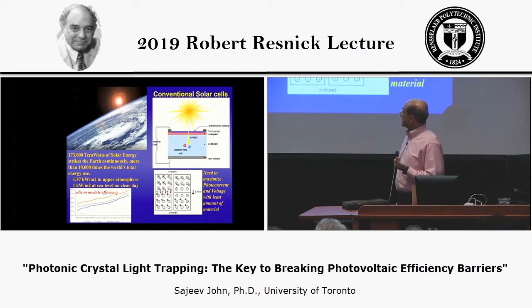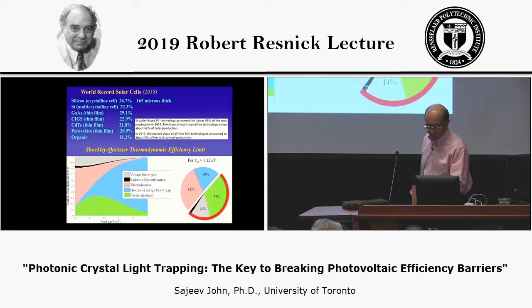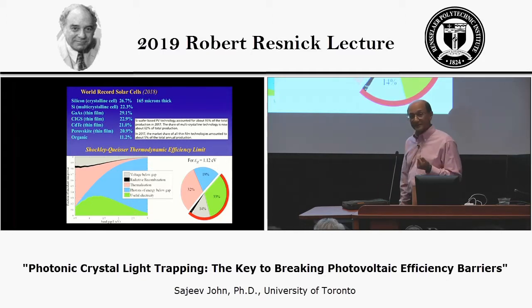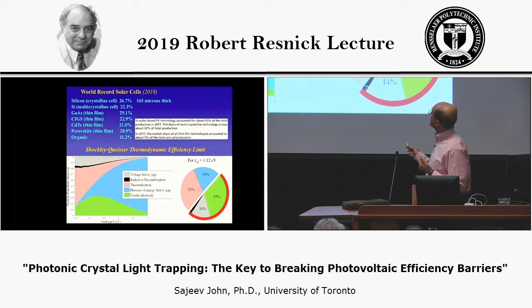And typical silicon materials that we have right now, the module efficiency has been growing slowly over time. Right now, if you buy a silicon solar cell or a module, its efficiency is in the 17 to 20% range. In terms of laboratory solar cells, there are a number of world records that have been set that are much higher than those module efficiencies. And just last year, the efficiency of crystalline silicon went up to 26.7%. That was done by a company by the name of Kaneka in Japan. And the cell thickness there was 165 microns of silicon. If you have multi-crystalline silicon, the efficiency record is down to 22.3%. There are more defects in the structure and more places where the charge carriers can recombine.